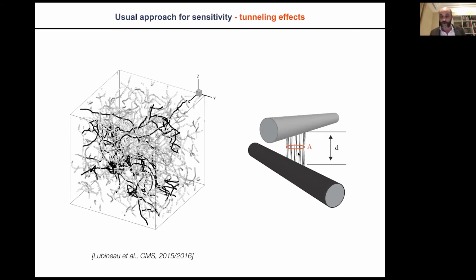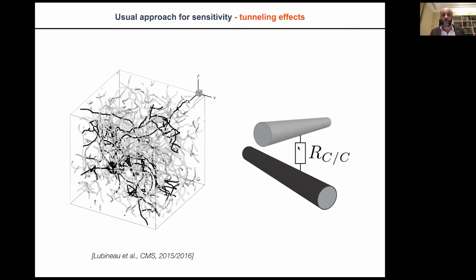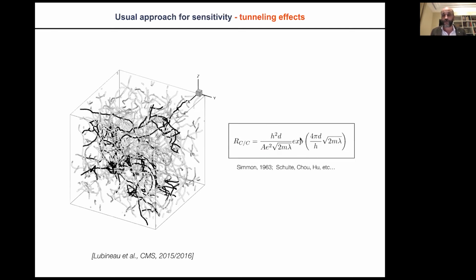And you know that if you look at this from a microscopic point of view, with some distance and some effective cross section, you can, at a very low level, approximate this by a resistance of the interaction between the two particles. And this resistance is well known to be exponential in the distance between the particles. So this is the basic phenomenon that you are using in any kind of piezoresistive nanoparticle-based sensors. That means you have a cloud of particles with some resistance, and as soon as you start to increase a little bit the separation between the particles, you will get an exponential increase in the effective macroscopic resistance.